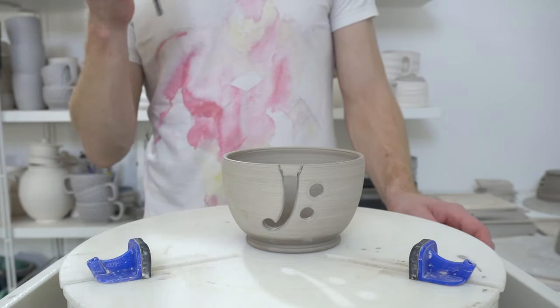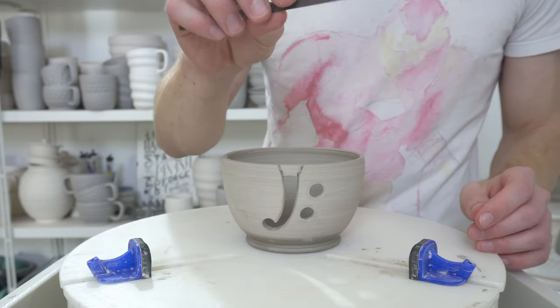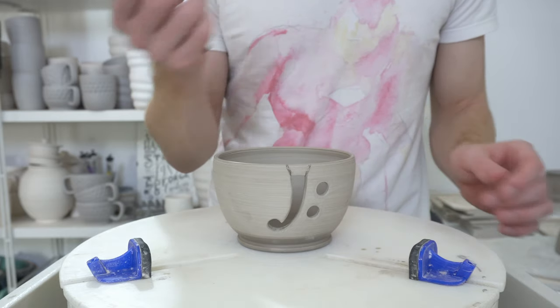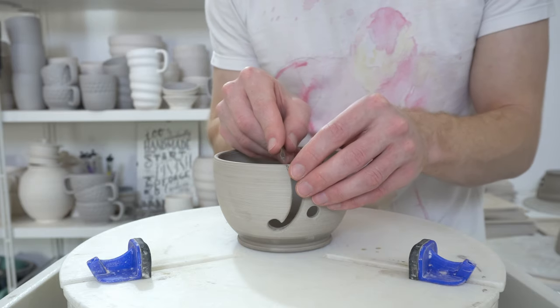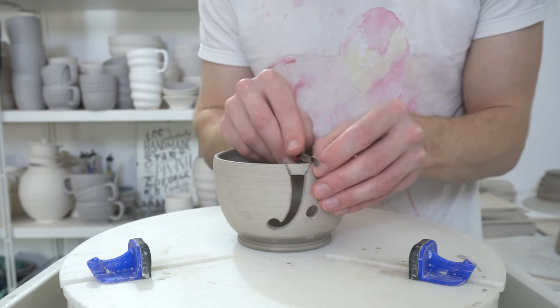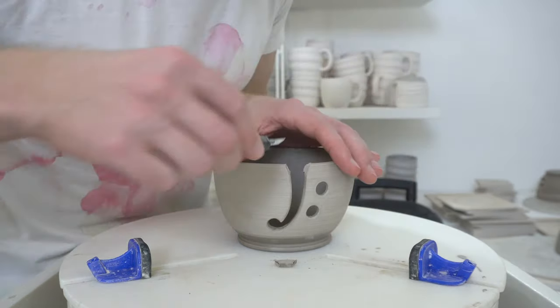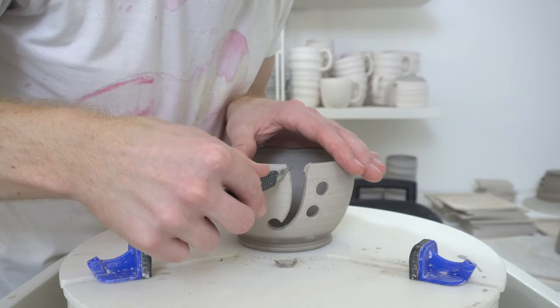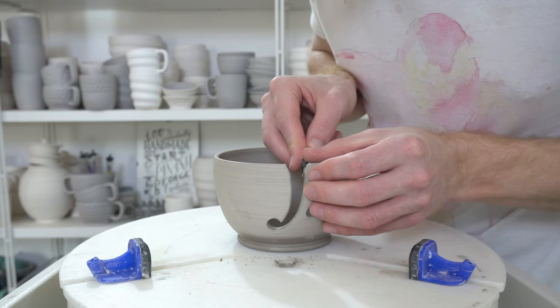This is the next day — not quite bone dry but pretty dry. I've got an old hacksaw, it's actually a jigsaw blade, but you want something with a fine tooth. If I'm going to do more of these I'm going to get a better one because this one's a bit wobbly, but it's just one that was kicking around in the garage. With a fine-tooth blade you can just very gently ease through the clay and it'll crack along the lines that you scored in. You can still use a scalpel to clean them up roughly and then sponge to finish the job off.